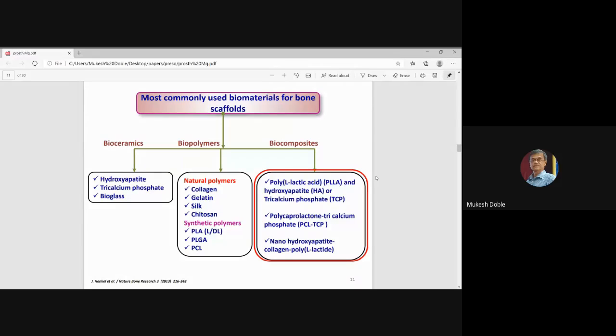So you can think of coating metals like stainless steel or titanium with these type of composites, because as you know, hydroxyapatite, tricalcium phosphates are very biocompatible, almost like your bone. And you could have polymers which are biodegradable, which is also biocompatible. They allow cell adhesion. We can have drug encapsulated with the polymer so that the antibiotic could be acting against the bacteria, or we can have growth factors incorporated into the biodegradable polymer. So the growth factor could enhance adhesion of the scaffold with the host cells. So we could think of designing different types of material for different applications. If you're looking at biofilm prevention, antibiotic could be there. If you're looking at growth factors or anti-inflammatory molecules, we can think of them, and so on actually.